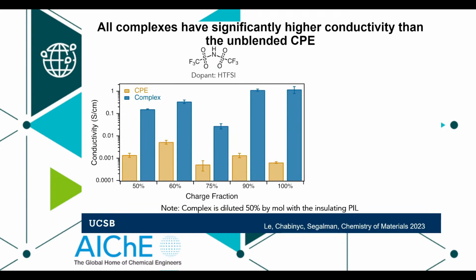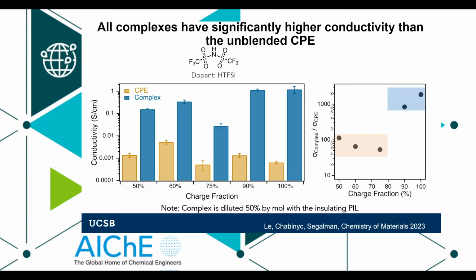In fact, if I plot it slightly differently and with better error bars, you see that it's frequently a lot more than 2 orders of magnitude. In some ranges of charge fraction, we're more than 3 orders of magnitude higher in the complex as opposed to the polymers from which we made it, in a system in which we've dumped in more than 50% insulator, right? So we've got 50% conductive loading and much, much better performance, right?